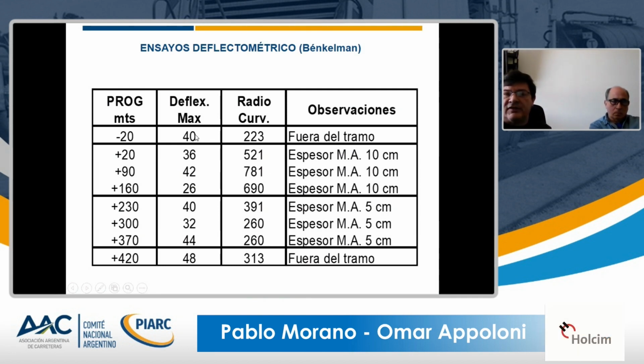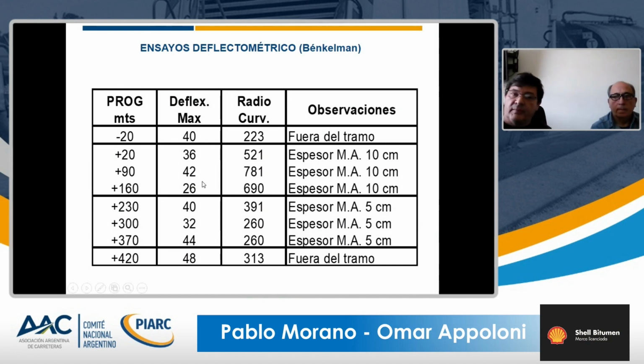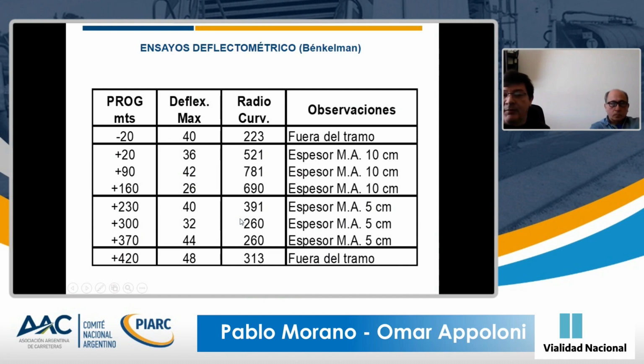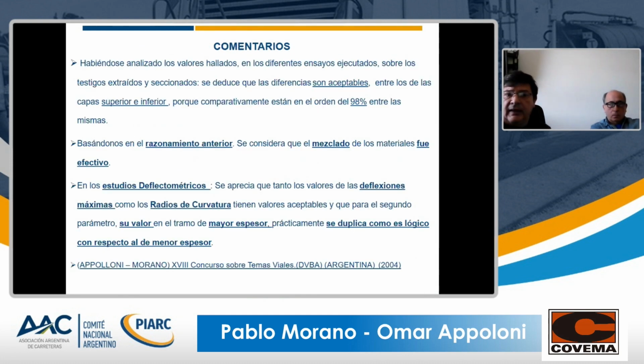What we could see here is that both when we used lime granular stabilization and 18 centimeters of asphalt layer, the measurements for the surface were matching what happened with 5 centimeters of asphalt layer, and it was a little better. And when we had 5 more centimeters in the asphalt layer, deflections drop, but the curve radius are increased. The conclusion is that with this type of base, the contribution of new layers can be decreased substantially and obtain big savings. This comment is the explanation that I just gave you.